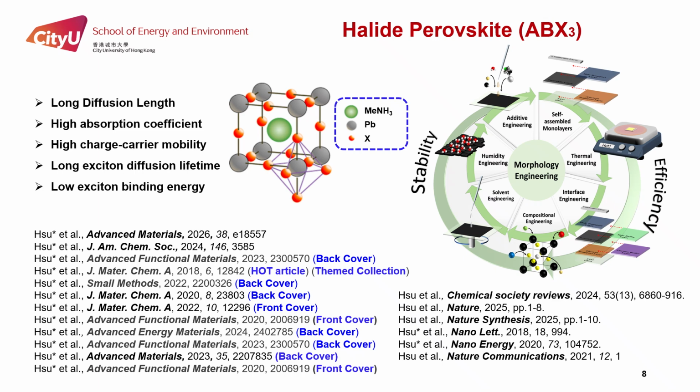Another hybrid material we are interested in is organic-inorganic halide perovskite. Halide perovskite with the ABX3 structure has been recognized as an attractive material for various energy applications, because this kind of material exhibits outstanding electronic properties. Here is the structure of a methylammonium lead halide perovskite, which is formed by three components consisting of organic cation, bivalent metal cation, and anions, with the octahedral phase of lead iodide.